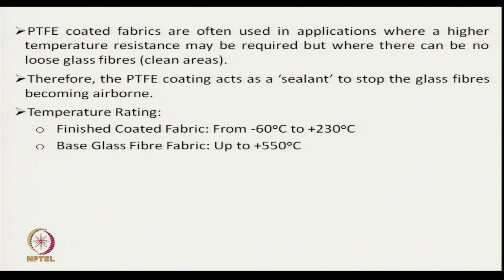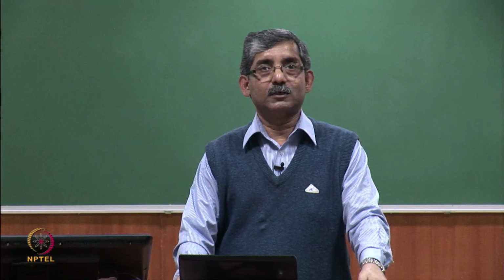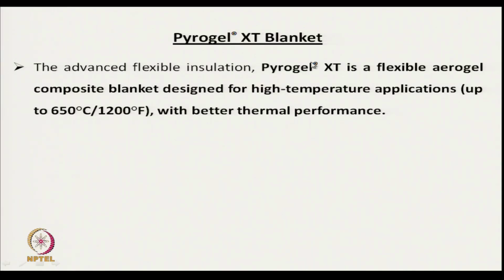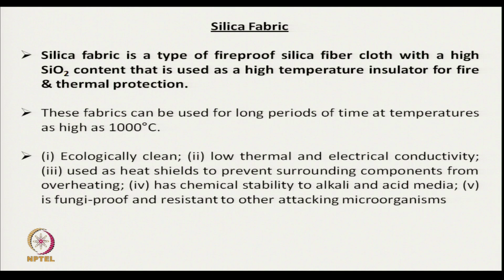The temperature rating of the coating is minus 60 degree Celsius to 230 degree Celsius, and the base glass fiber is up to 550 degree Celsius. So, although glass fabric has a higher temperature rating, this PTFE works up to around 230 degree Celsius. Pyrogel XT blanket is basically produced from aerogel; it is an aerogel composite for high temperature application. Silica fabric is also used for high temperature insulation and thermal protection.